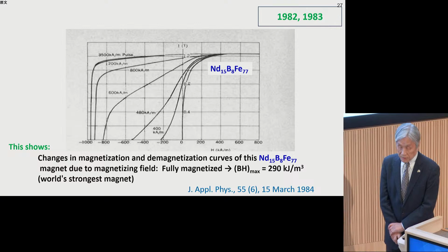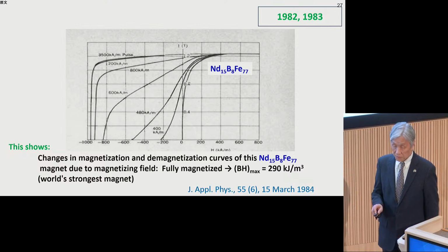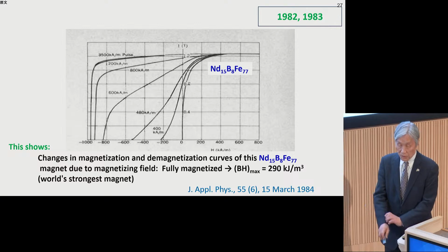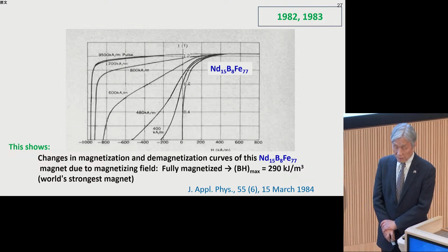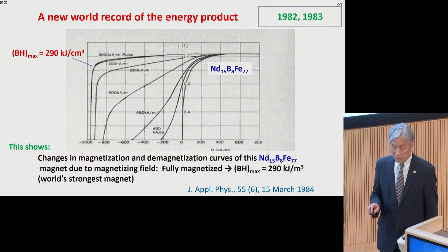This shows changes in magnetization and demagnetization curves of this neodymium 15, boron 8, iron 77 NeoMax magnets due to magnetizing field. And fully magnetized BH maximum shows 290 kilojoule per cubic meter. This is the world's strongest magnet. This is a new record of the energy product.